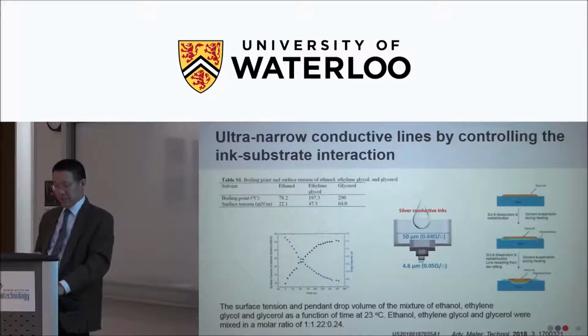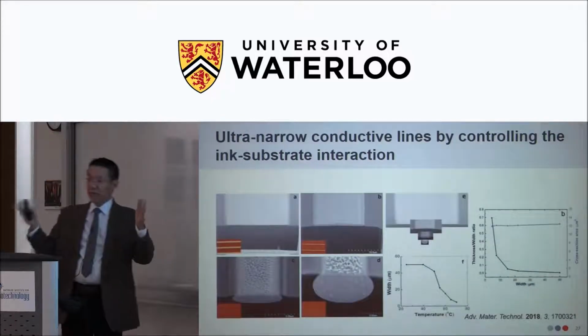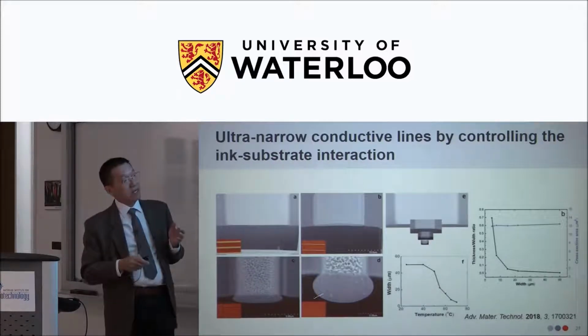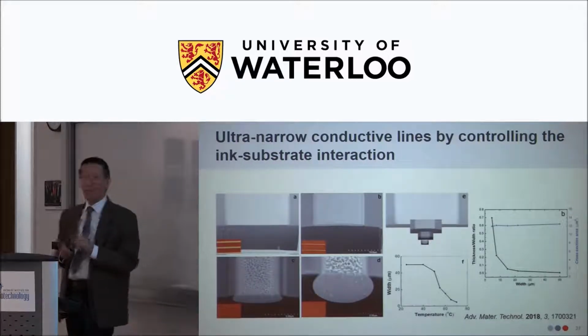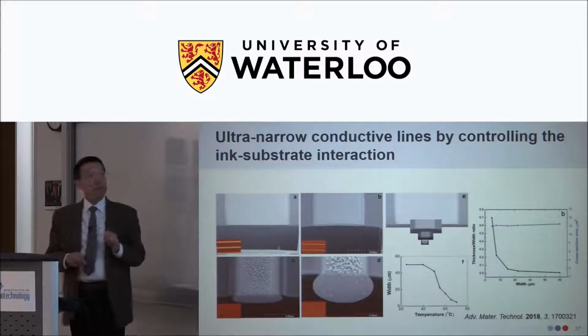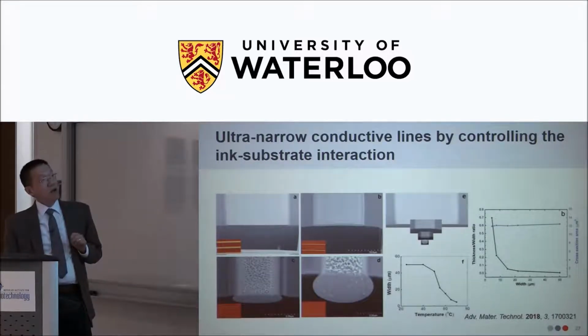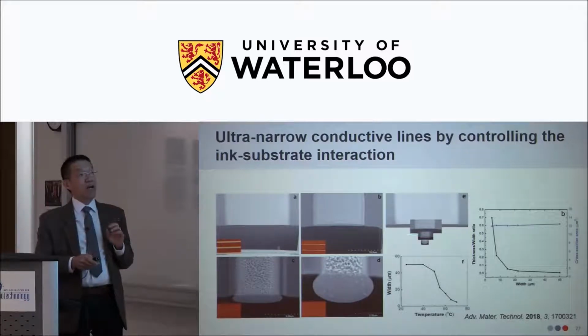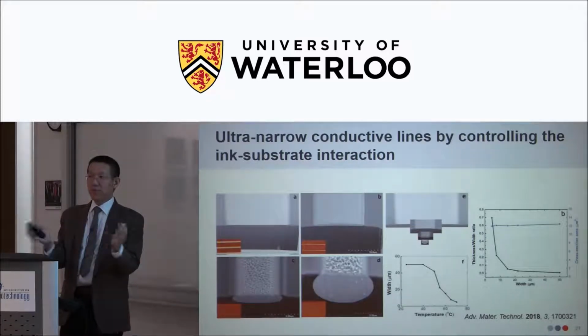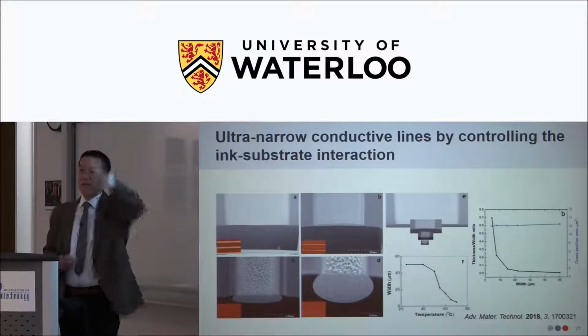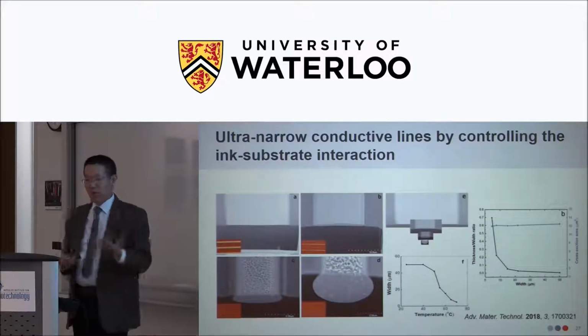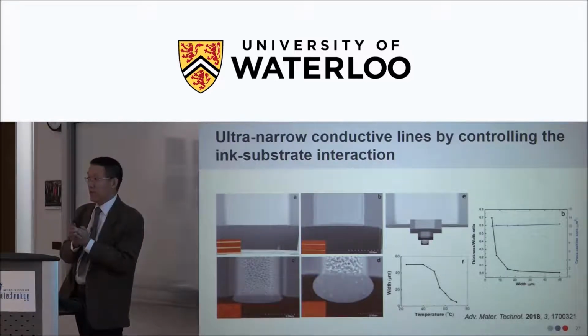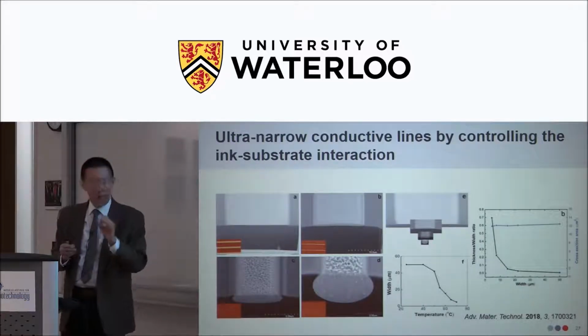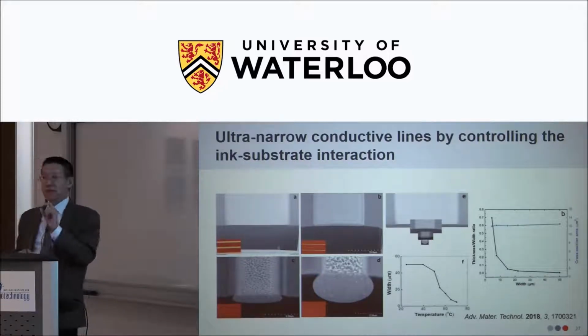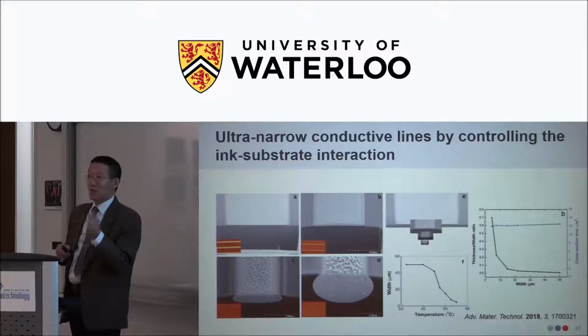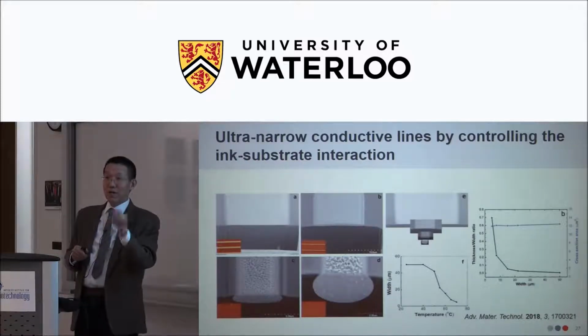Okay, so that process can reduce the 50 micron wide line down to 4 micrometers, but the thickness increases, right? When you look at the cross-section, the total cross-section of the line remains unchanged, but it just trades the width for the thickness of the line. And that is one way to make high-resolution printing or extremely narrow lines. But the narrowest width of the line will be determined by the initial amount of ink you dump on the substrate.